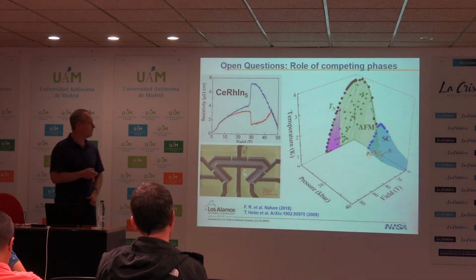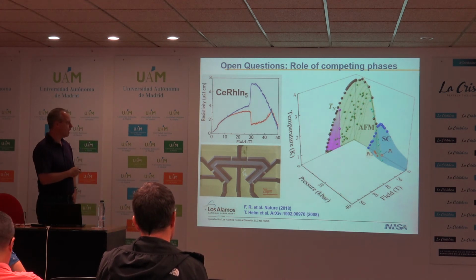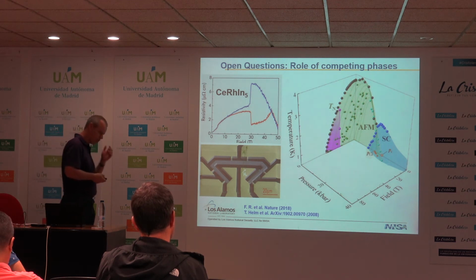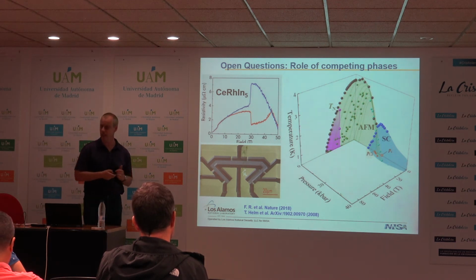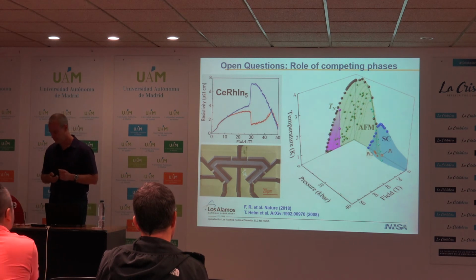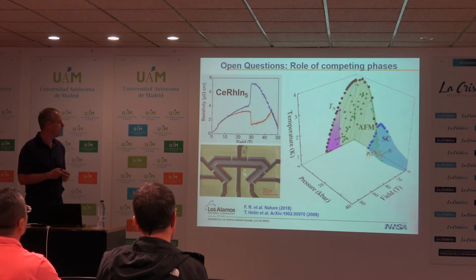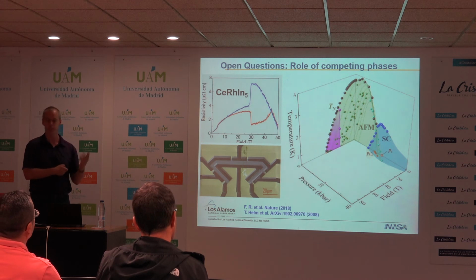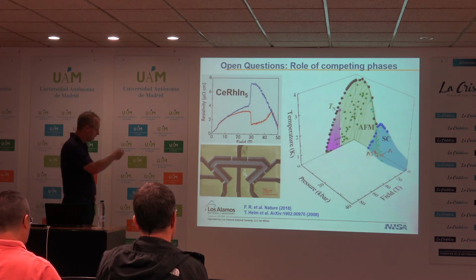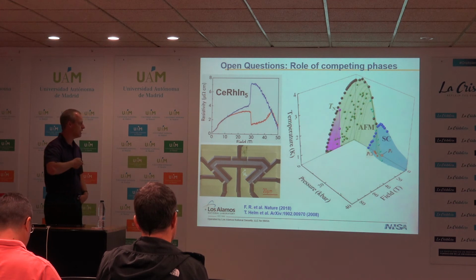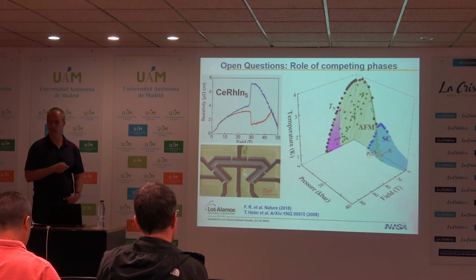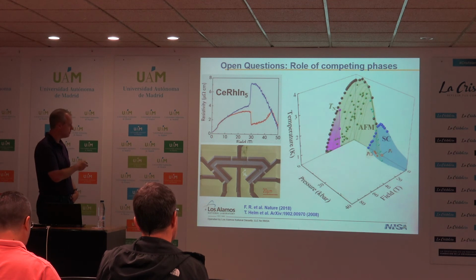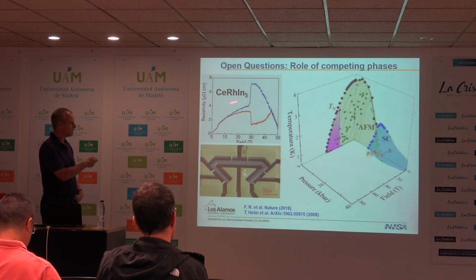Okay. Competing phases, I bring this up mainly because we heard earlier in the week about nematicity in the pnictides in particular, and the role that nematicity might be playing in superconductivity. In heavy fermions, again, we have an example of something that looks a lot like a nematic phase transition. So here's resistivity as a function of magnetic field. This is this antiferromagnetic compound, so we're sitting in the antiferromagnetic state. And you see a dramatic change in the resistivity.